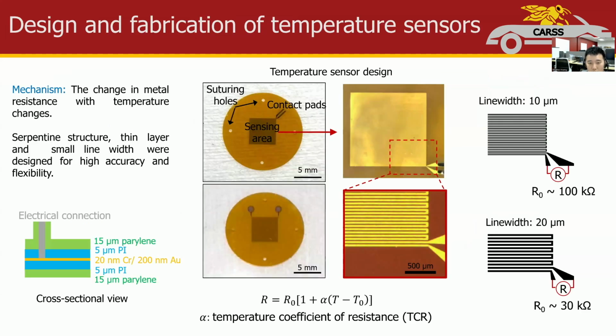The mechanism of our temperature sensor is the resistance change effect of metal thin film when temperature changes. Briefly speaking, resistance of temperature sensor varies linearly with temperature. Here, we use the small line width, thin layer, and serpentine structure to amplify this temperature sensing effect, thereby increasing accuracy and flexibility. Using classic lithography-based method, we fabricated these temperature sensors. The main line widths are 10 micron and 20 micron, and the resistance are 30 and 100 kilo ohms.